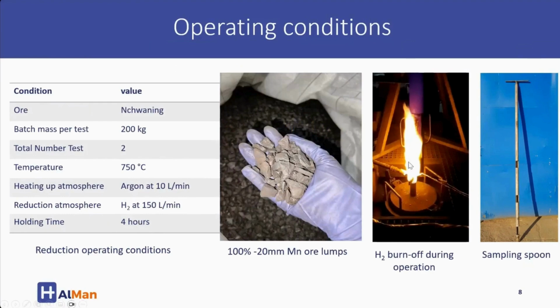You can see the flame roaring during the hydrogen reaction. At the end of the test, we used a sampling spoon with 3 openings at different heights to sample at different heights through the burden.